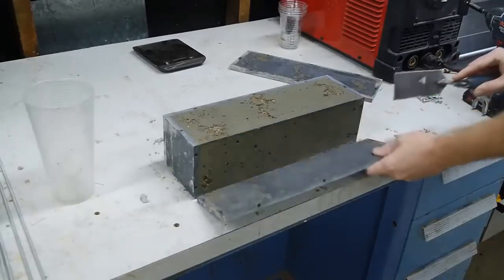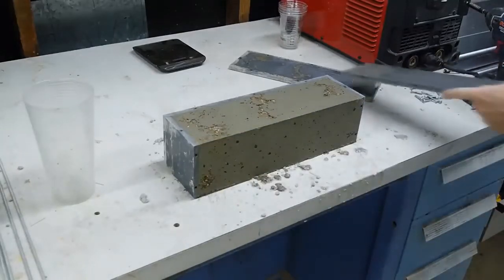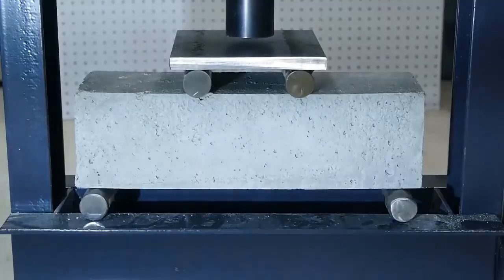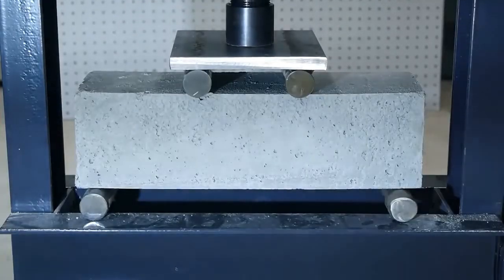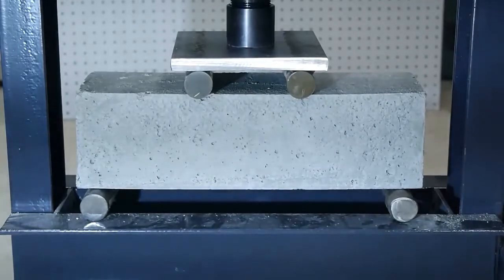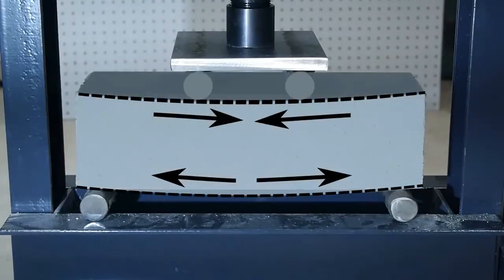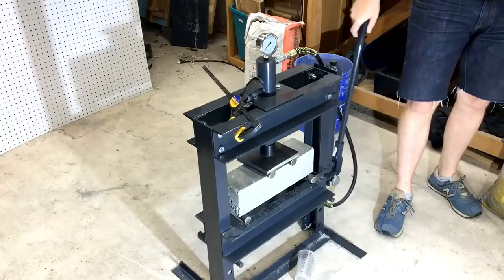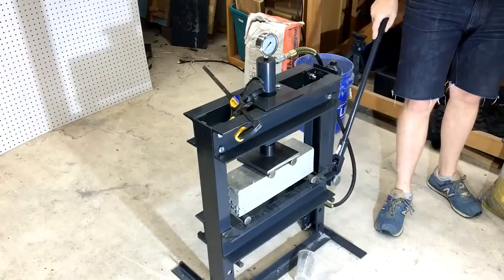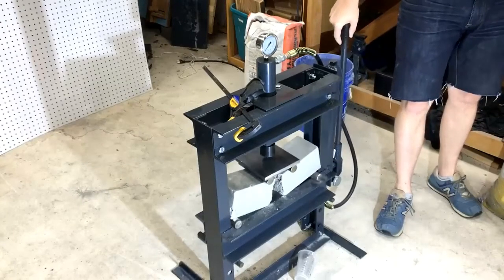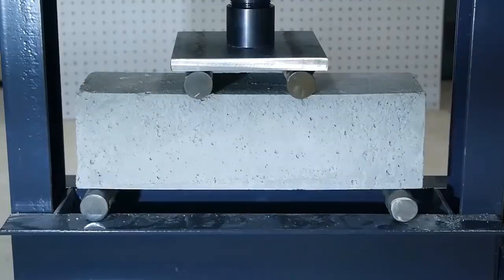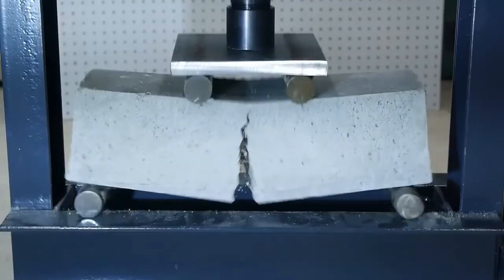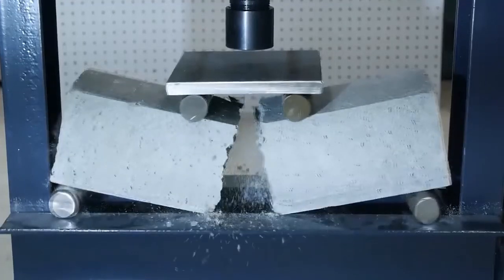This particular classic beam is homemade by me out of pure concrete here in my garage. Applying a force on this beam causes internal stresses to develop, and here's what they look like. The top of the beam experiences compressive stress, and the bottom of the beam experiences tensile stress. You can probably guess where the failure is going to occur on this concrete beam as I continue to increase the load. It happens almost instantly, but you can see that the crack forms on the bottom of the beam, where tensile stress is highest, and propagates upward until the beam fails.